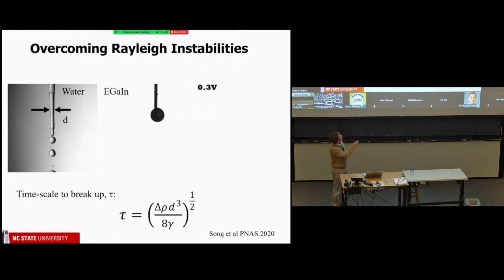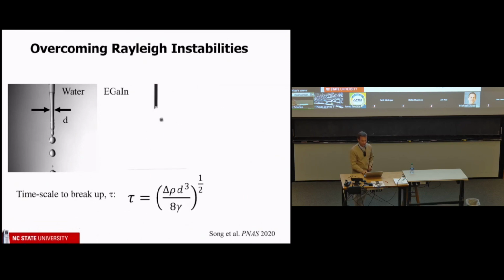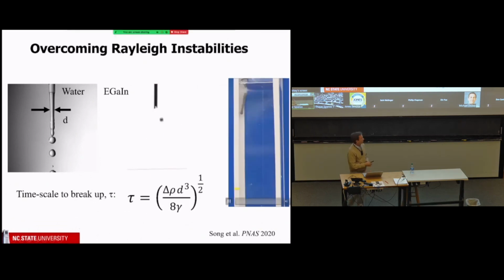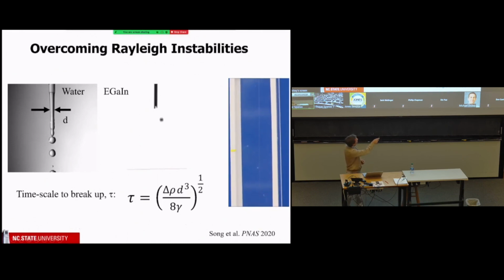But if you start applying the voltage, which you can see here, we lower the surface tension because of this oxidation, and it will come out as a hair. The diameter of this is 100 microns, the same as a human hair. So we're taking the liquid with the largest surface tension known to man, and we're making a little hair. So here we've got the tallest container we could find in my lab. My daughter refuses to cut her hair, so it's really long. It's like my daughter's hair. So it's this tall, but it's 100 microns in diameter.